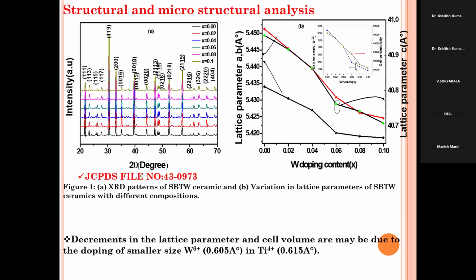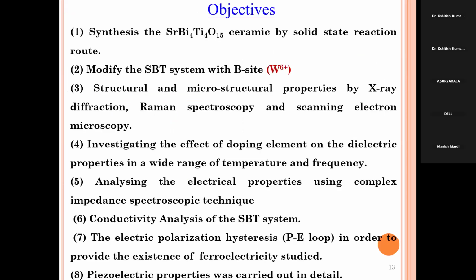For the structural characterization, we conducted XRD. Most people know what XRD is, but let me explain how we prepared the sample. We took strontium carbonate in powder form, bismuth oxide in powder form, and titanium oxide in powder form. For a 10 gram preparation of SBT, there is a stoichiometric calculation. According to that calculation, suppose strontium carbonate is 2.01 something, then bismuth oxide is 3 point something, then titanium oxide is 1 point something, and the total equals 10 gram. We weighed the materials in a weighing machine and mixed them in an agate mortar.